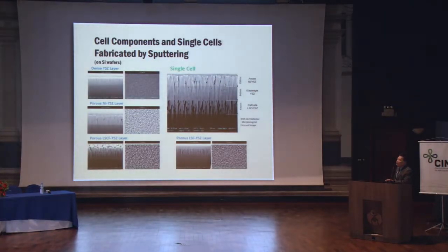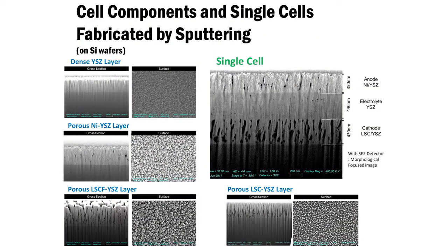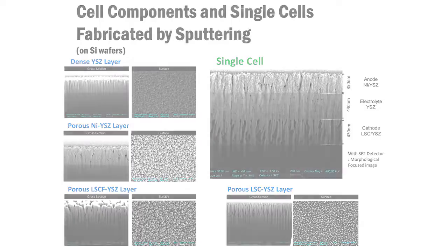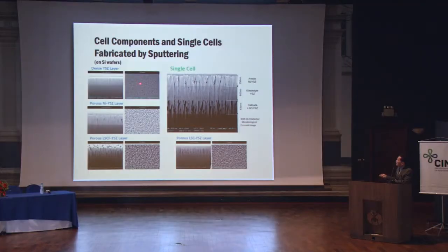And we have developed a process, and initially we use a silicon wafer as the substrate to develop the process. And we have defined the various process procedure conditions. So we developed a dense yttria-stabilized zirconia electrolyte, or YSZ electrolyte, fully dense. You can see here the cross-section and also the as-deposited surface.